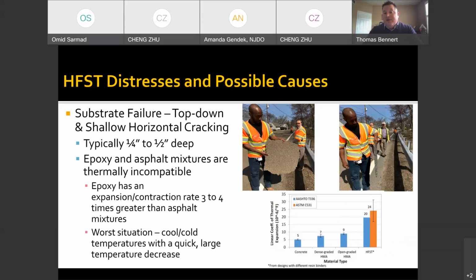So you can see here's Stevenson Ganthier, formerly of New Jersey DOT Materials, now NJDOT Construction, showing a panel that we found on the side of the road. And that's about a half inch thick. And if you look on the other side of that panel, you'll see that that's really the top layer of aggregates and asphalt from that section.